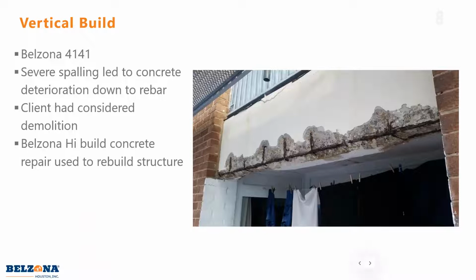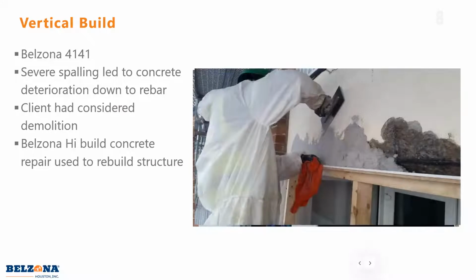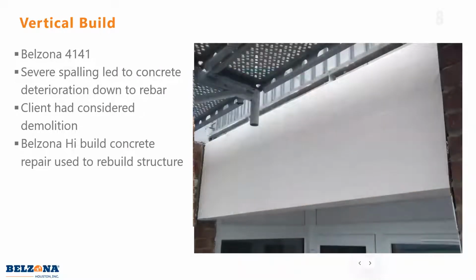You see the spalling led to the deterioration, all the way down to the rebar here. So what they did, came in here, used Belzona 4141 to form it. As you can see, there's no actual former that needs to be poured. There was a small former set to the bottom, as you can see, just to give it a good straight line. Not really to hold it up, but it'll give it a nice, good flush line. So at the end, you can see the final result here.